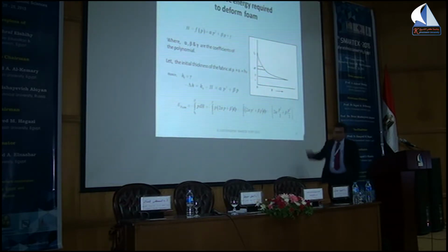So these are the two equations characterizing the energy: the left hand side describes the energy released by the fabric, and the right hand side describes the energy released because of the compression of the foam that you get. And you have to equate these two. Before that, we need to know the constants which are there.